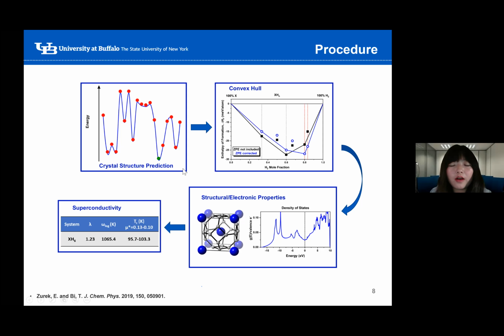Once we get a collection of the global minima structures for several stoichiometries, we would plot the enthalpy of formation against the hydrogen content to construct the two-dimensional convex hull. Any structure that's located on the hull is considered thermodynamically stable. And for the dynamic stability, we use either the phonopy or Quantum Espresso package to calculate the phonon spectrum. For the thermodynamically and dynamically stable structures, we will analyze their structural and electronic properties. And for the promising metal structures, we will also calculate their electron-phonon coupling parameters using the Quantum Espresso package and estimate their TCs using either the Allen-Dynes modified McMillan equation shown earlier, or for the systems with large lambda, we would also calculate the Eliashberg TC.